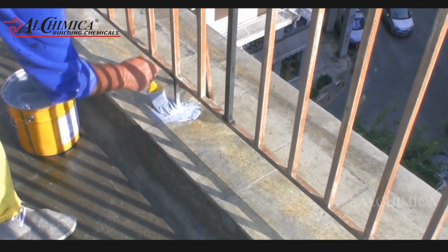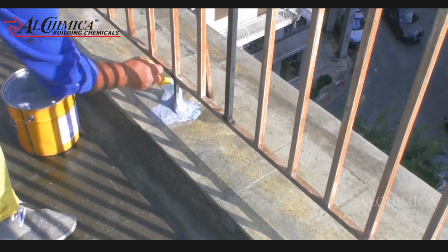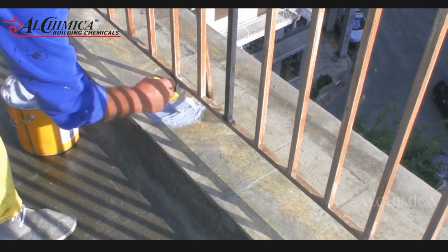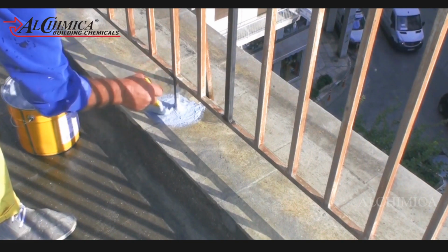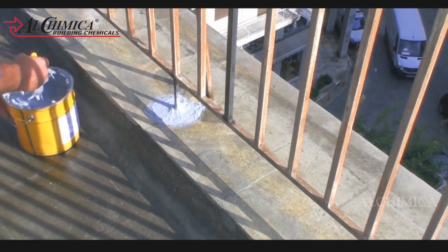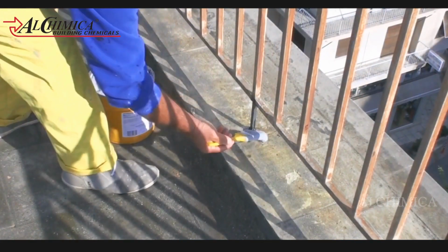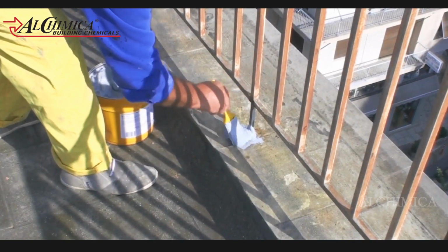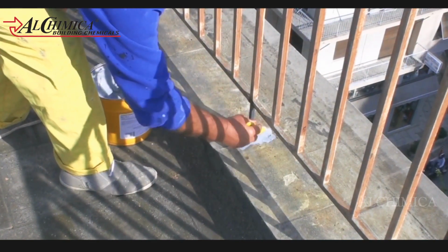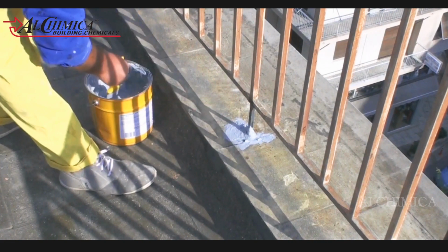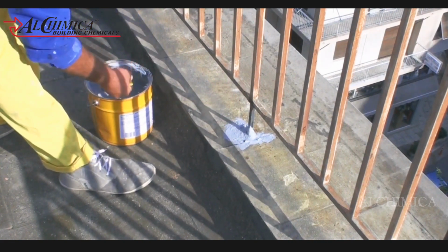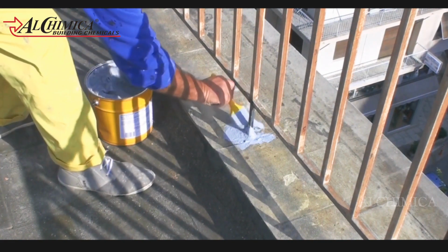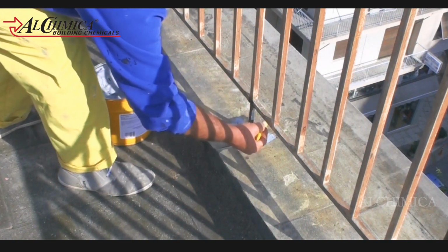Hyperdesmo Classic is then applied with roller brush or spatula or spraying machine. Each coat should not exceed 700 to 800 grams per square meter per coat. We have some formulations in the Hyperdesmo range of coatings which can be coated to higher thickness in a single coat. Contact our technical team for details.